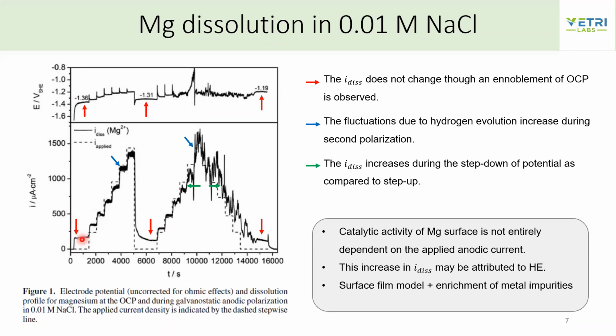So they tried to see the dissolution current at 3 different points. What they saw was that the dissolution current during the OCP at the first stage was similar to the dissolution that they observed after one set of anodic polarization. And then they were again able to see the same kind of dissolution current after a second set of anodic polarization. The steps are all similar, but we see that where polarization is here, the dissolution is much higher.